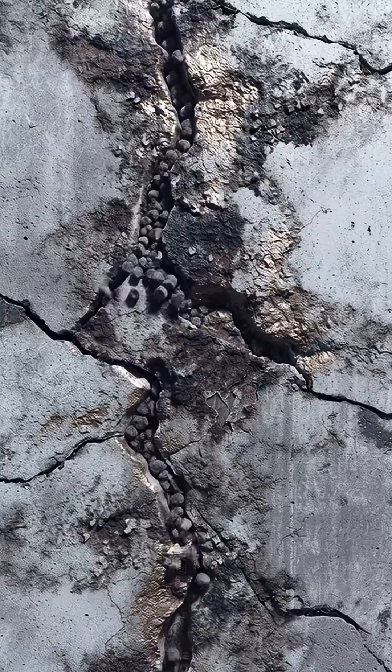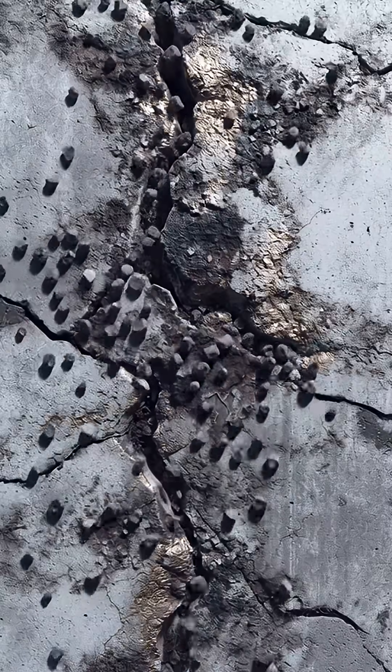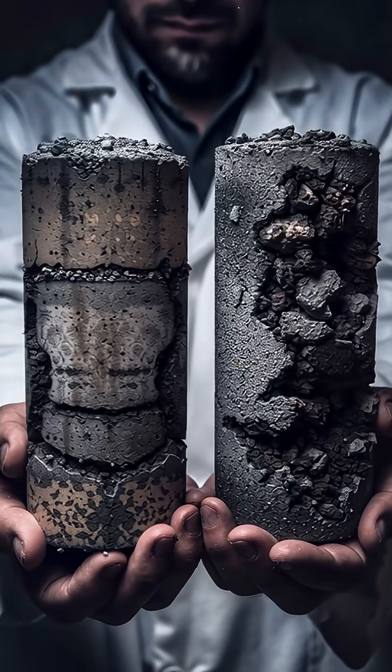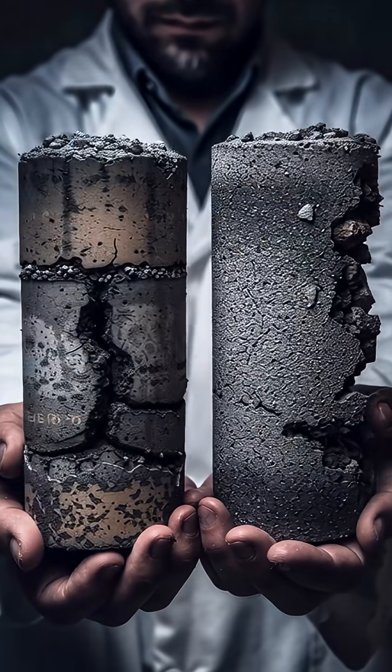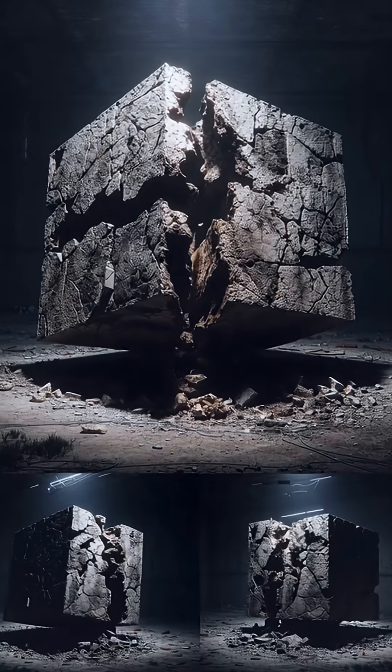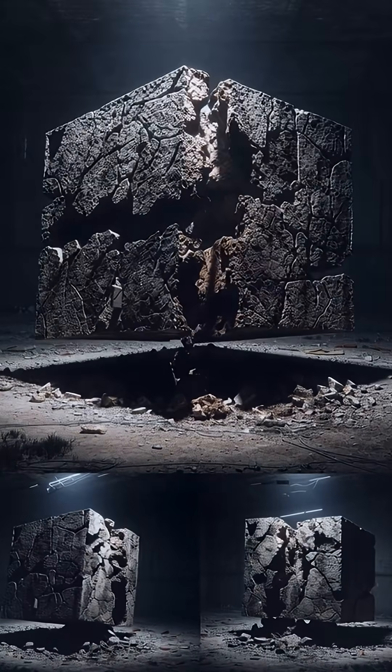The exposed material reacts to produce calcium-rich solutions that re-precipitate as calcium carbonate or react with ash, sealing and strengthening the matrix. In lab tests, hot mixed samples healed deliberate fractures within two weeks. Identical mixes without quicklime did not.